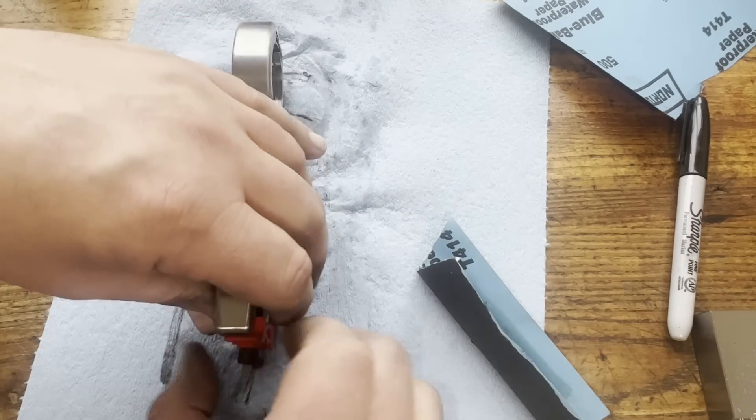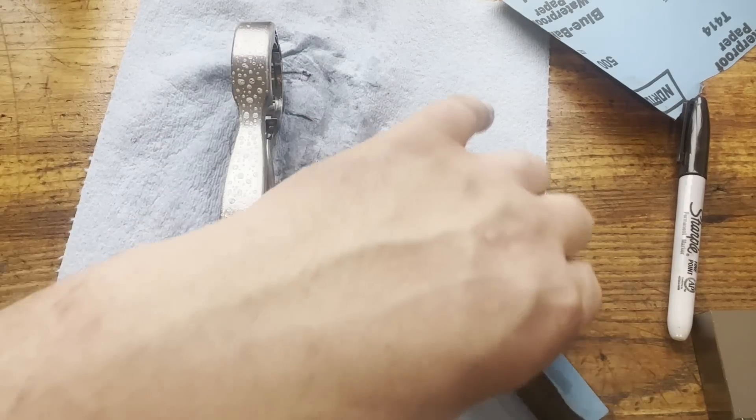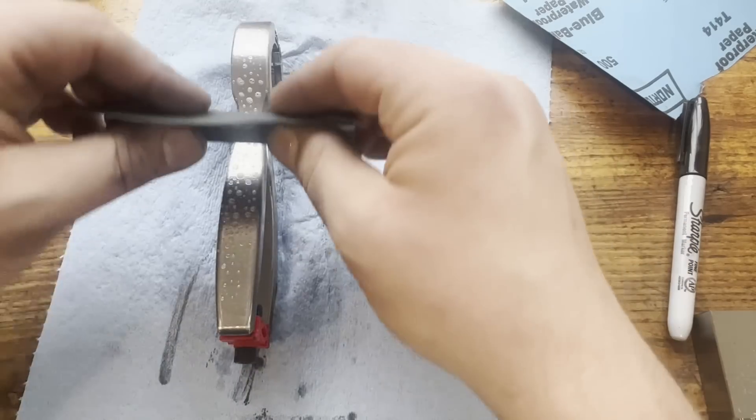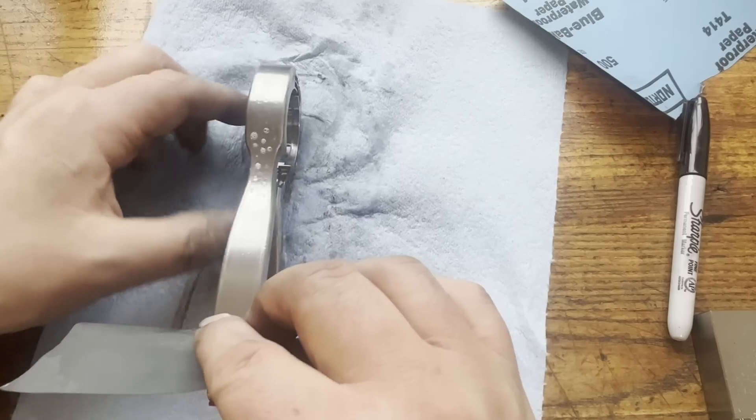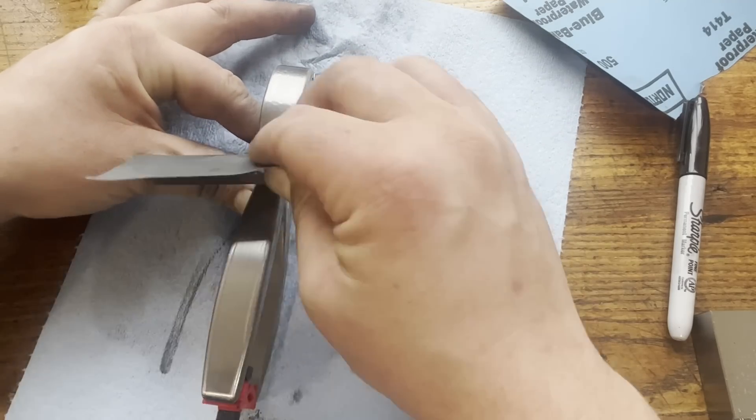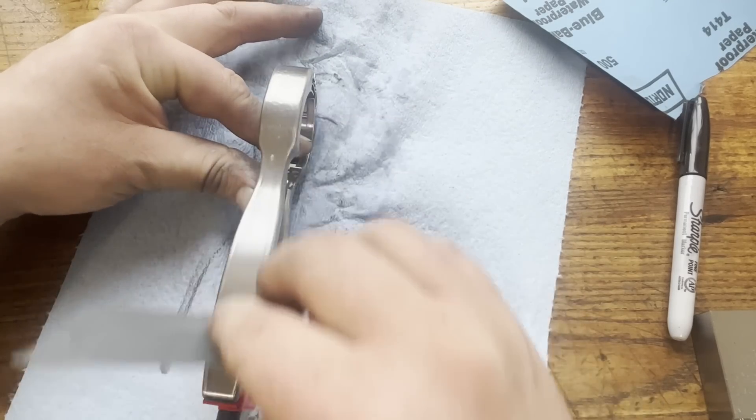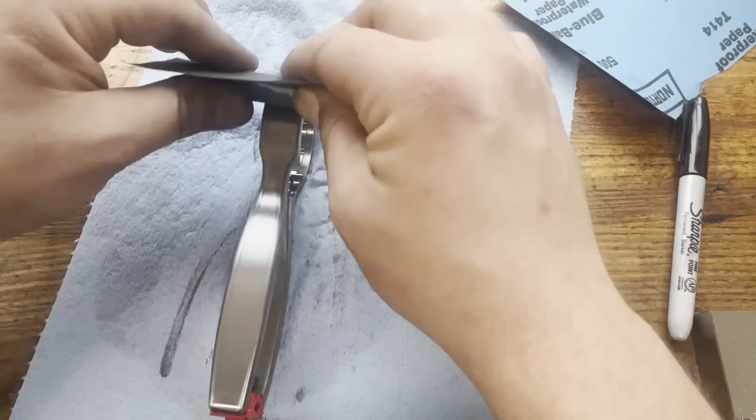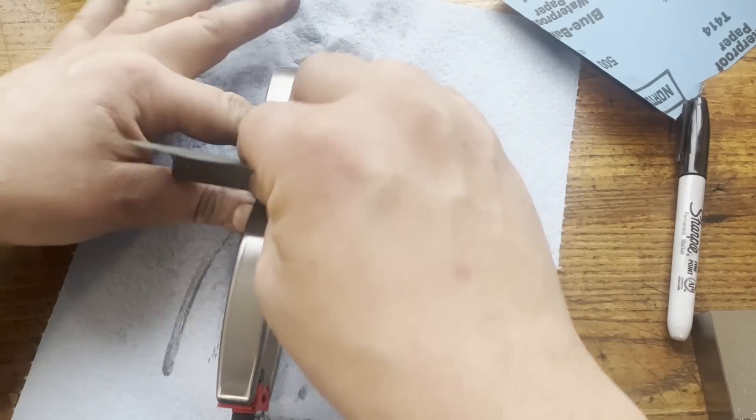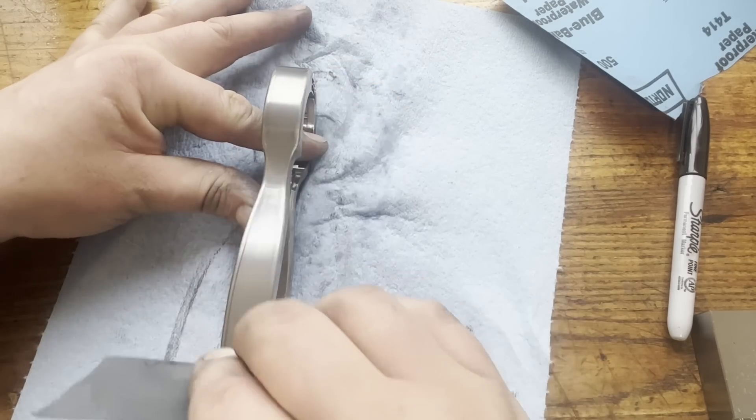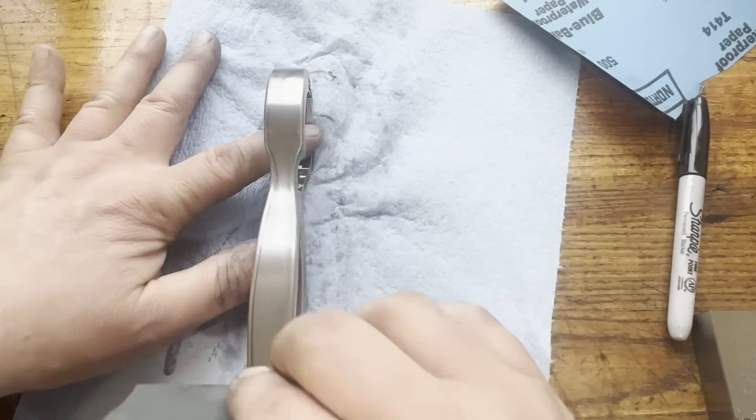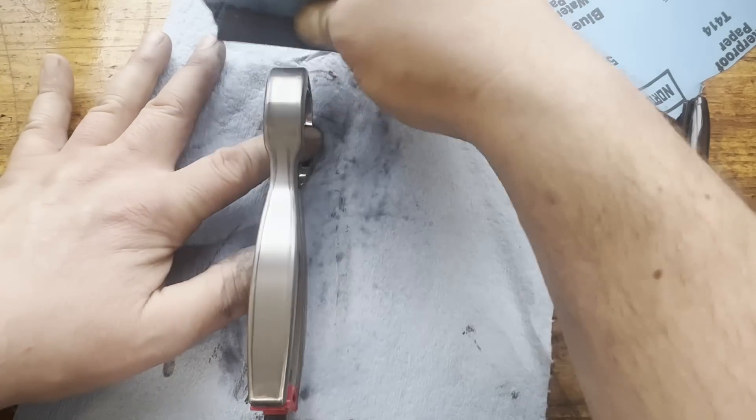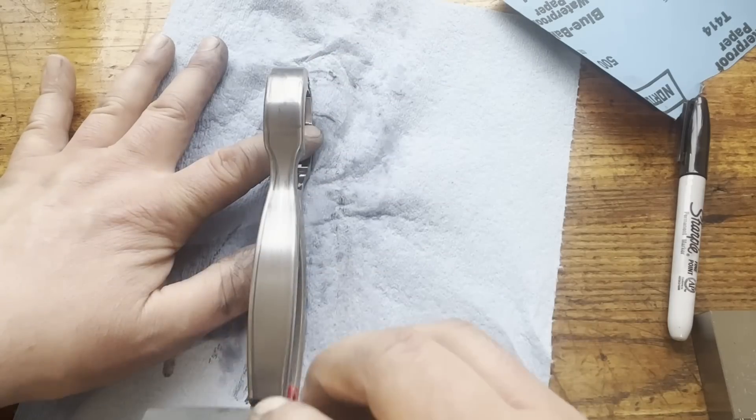Using that scissor jack earlier just so I have a little more firmness under so I can press down. When you're doing paper, even stone finishing like this, you really don't need to be pressing much. If you really bear down on it, you can actually kind of create deep scratches. And that's not what we're looking to do. We're just looking to remove the peaks of the feed lines or the previous paper finish. So light touch.